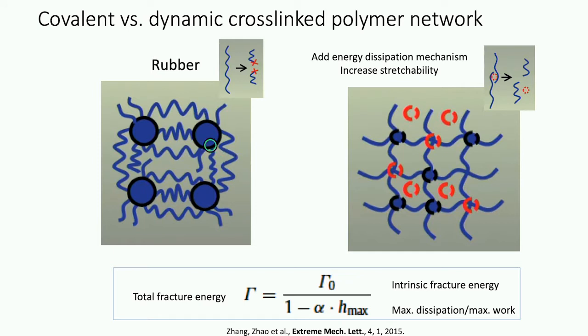But we're interested in a new class of material where this kind of network is formed using chemical bonds that are essentially reversible, or they are at equilibrium under room temperature. These chemical bonds can still break when the material is subject to strain, but they provide an energy dissipation mechanism so that the overall total fracture energy of the material can be increased. But the nice thing is these bonds are reversible, so the material can recover its original mechanical property or even electrical property because of the self-repair of these chemical bonds.